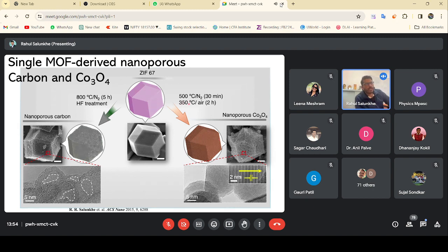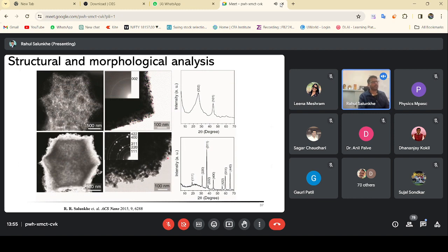And when we heat it at 350 degrees centigrade in air, the outside material is a nanocrystalline metal oxide, or a nanoporous metal oxide, we can say. So if we see the HRTEM images, very high crystalline fringes can be observed on this kind of nanogranular surface. Whereas if we heat in the nitrogen environment only, we get the nanoporous carbon with highly porous surface. In case of an asymmetric supercapacitor, we typically use activated carbon as a counter electrode. Whereas in this study, we try to develop two kinds of materials from one parent MOF, and we try to use them for the supercapacitor application.